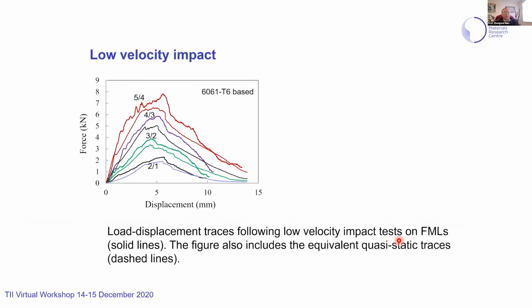Now this is force against displacement. We use a high-speed camera to record the displacement, and a dynamic load cell to record the loading. Again, there are four different stacking sequences: 2/1, 3/2, 4/3, and 5/4. We have paired lines. The lower one is from the quasi-static perforation, and the upper one is from the impact test. So we can clearly see some dynamic effect.